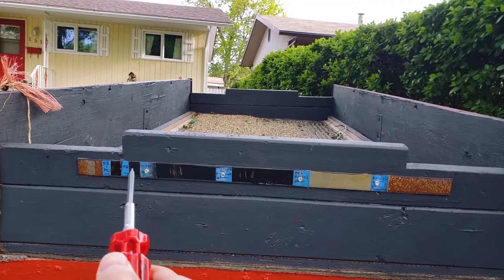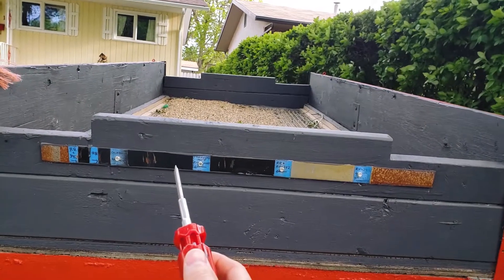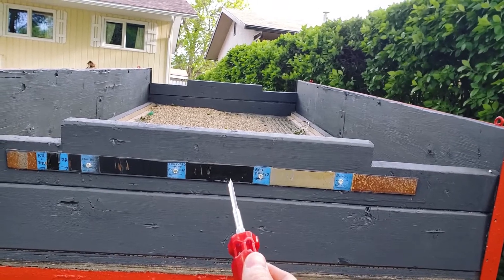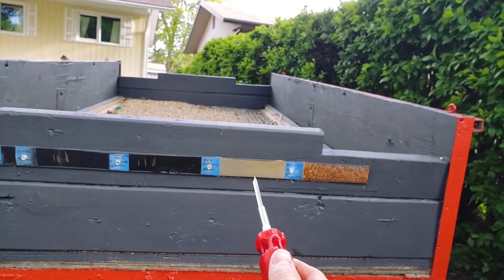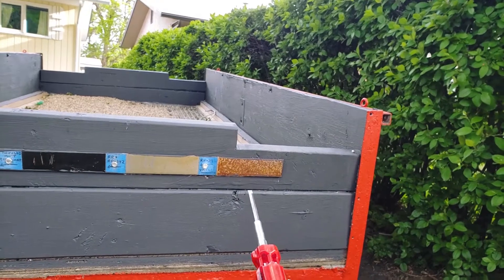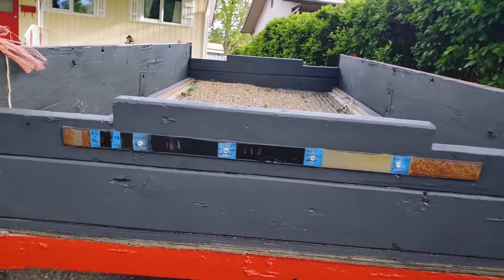I think those patches have been there for three to six months and looking good. This right here is just Tremclad rust reformer, right next to that is rust reformer plus the Cosmoline RP342, right next to that is just the Cosmoline RP342 — it's kind of like a wax coating, really good stuff. Next to that was WD40, but that's since been wiped off, so that's null.